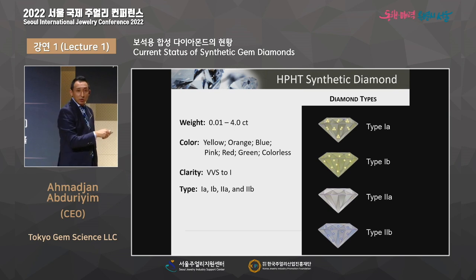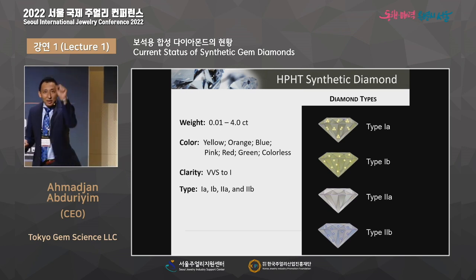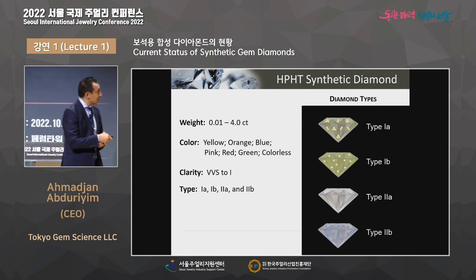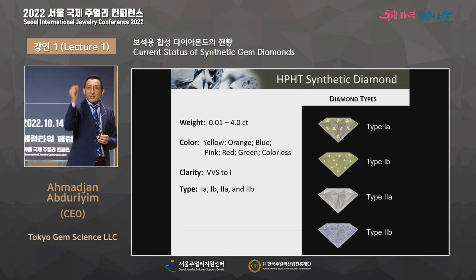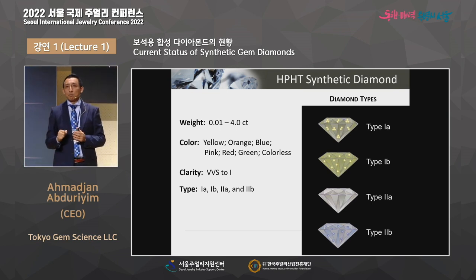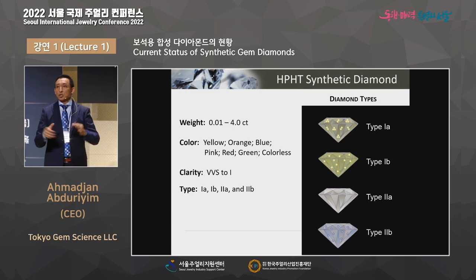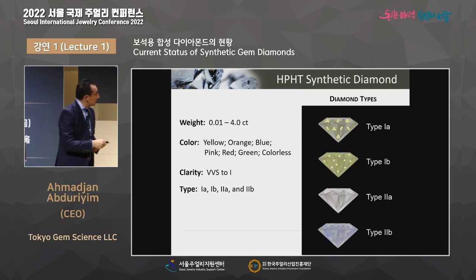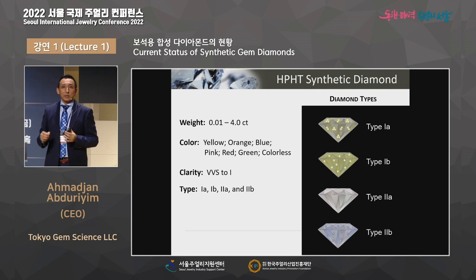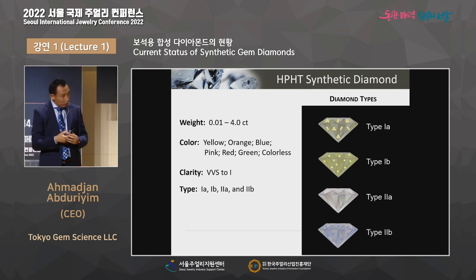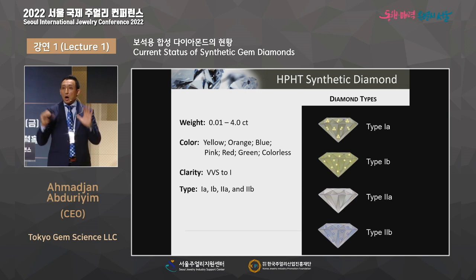And we have two others without any nitrogen, like type 2A. We call it type 2A diamond. The price is higher than type 1A diamond because it's extremely rare. You find one piece in 10,000 diamonds. And the color is really pure. We call this one the no-nitrogen type 2A diamond. And if you intentionally dope boron inside, it can form as in natural ones, like the Hope Diamond or the Wittelsbach diamond in the Smithsonian Museum. You will see the natural blue. However, artificial synthetic diamond can be created in the same color as well.